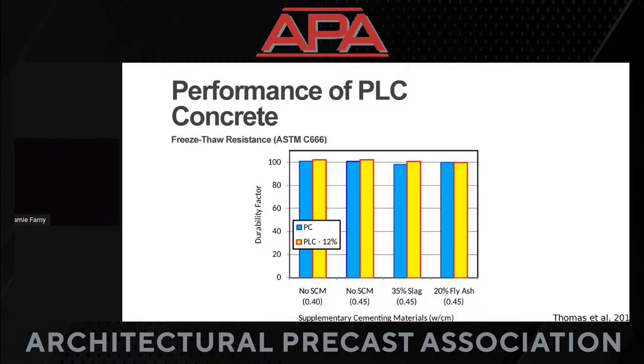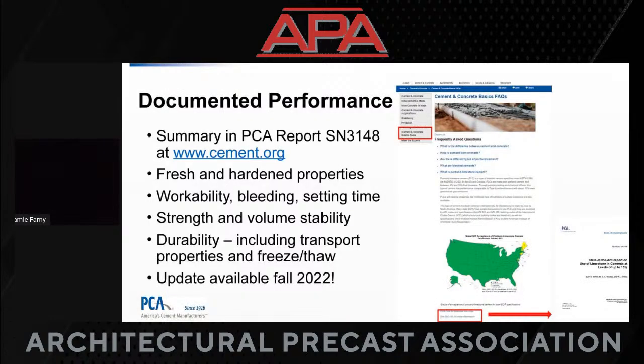We see that even at different water cement ratios, 0.4 and 0.45, with no SCM, you see very good performance. These are durable materials. They can freeze and thaw. They can be exposed to cold weather. They're not falling apart. If we add slag in at 35% or fly ash at 20% to either the Portland cement or the Portland limestone cement mixes, we still get across the board pretty much 100 durability factor. So that message here is these can be freeze-thaw durable materials. You don't have to worry that PLC is somehow going to make you non-durable in a cold climate.